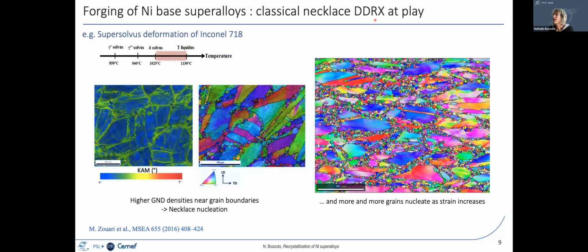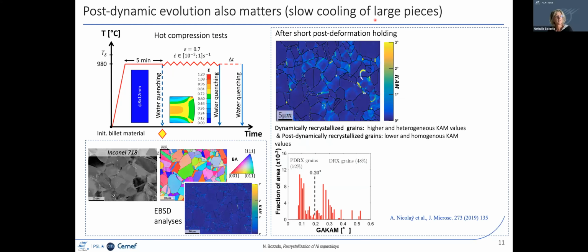But I would like to draw your attention to the fact that most people concentrate on what is going on during deformation. But if you deal with industrial pieces, which are quite big, they necessarily cool down quite slowly. And so you have to also consider what happens right after the deformation, which is the so-called post-dynamic regime. So at the lab scale, we are also doing experiments where the material is heated, deformed, and then we wait for some time before quenching it. This holding time is varied so that we can also analyze the kinetics of the post-dynamic evolutions.